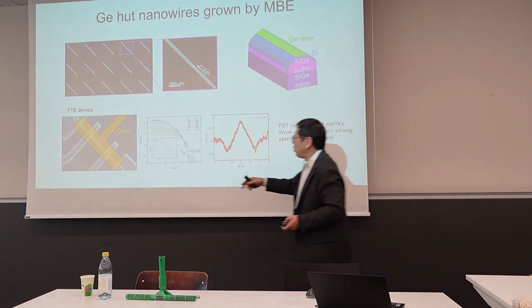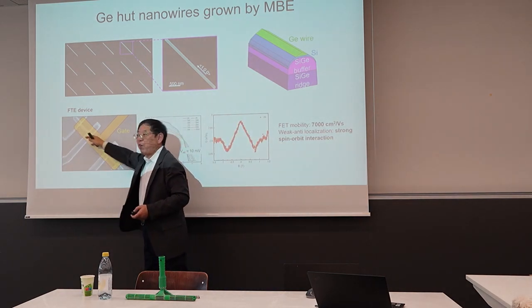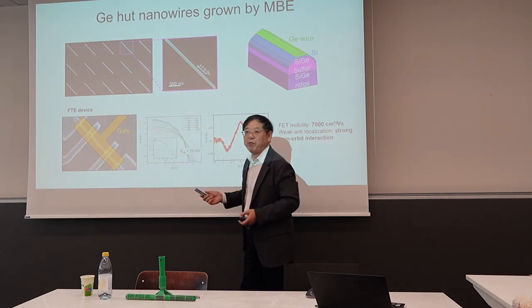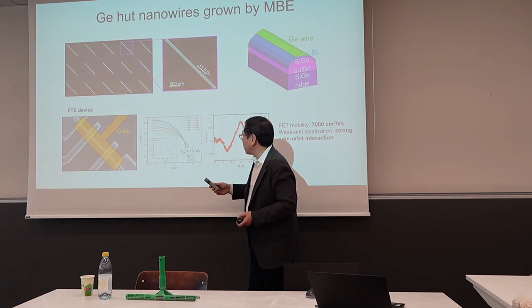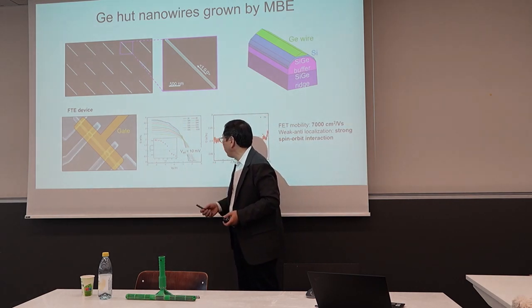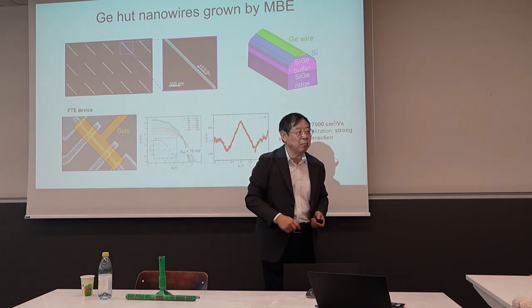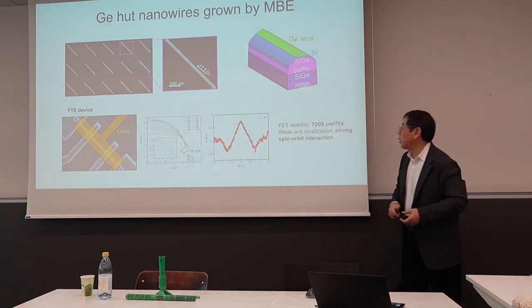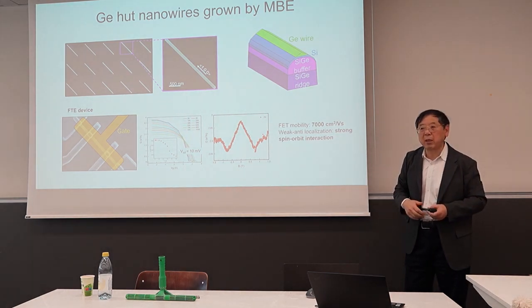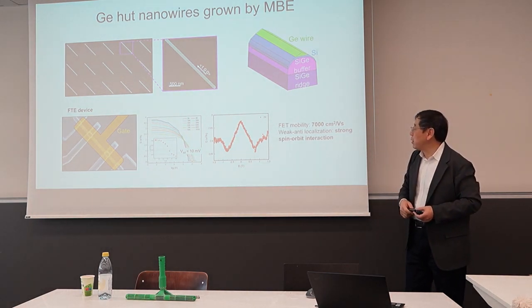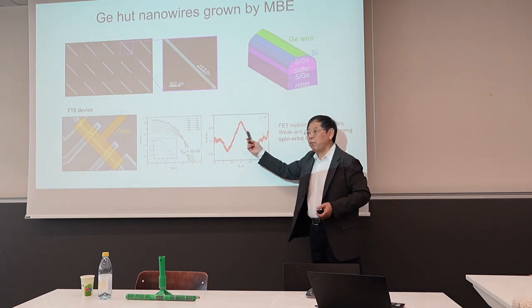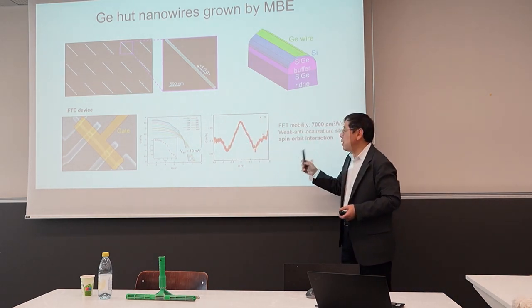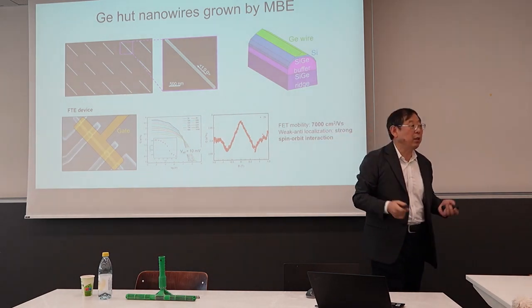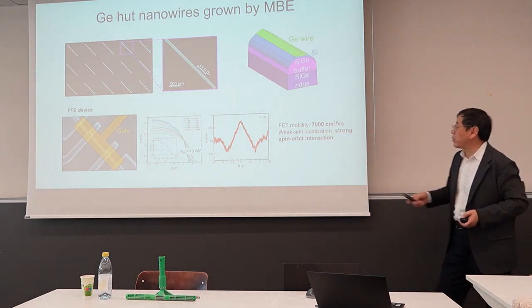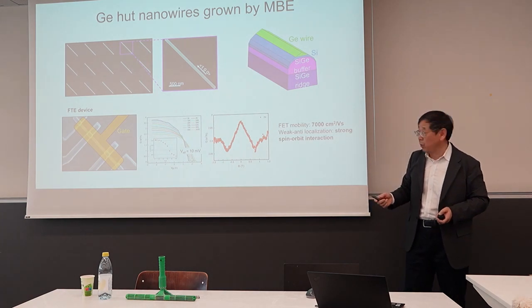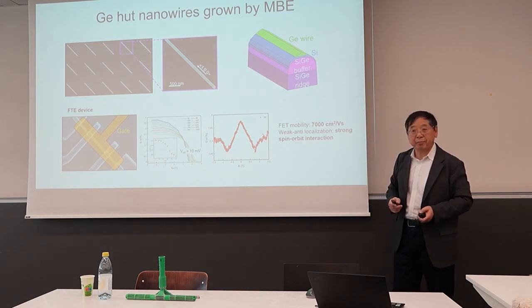But to characterize these wires, we just make a simple field effect transistor. And they show very nice field effect. You can extract field effect mobility with this one, which is around 7,000. So it's very good and almost similar to the indium arsenide standing nanowire. Then we see very strong weak anti-localization effect, indicating very strong spin-orbit coupling in the wire, which is what we need. We have not extracted the value yet, but we're going to do that also.